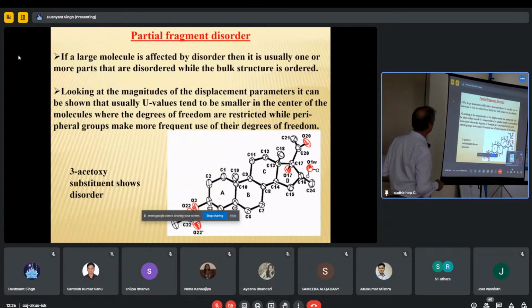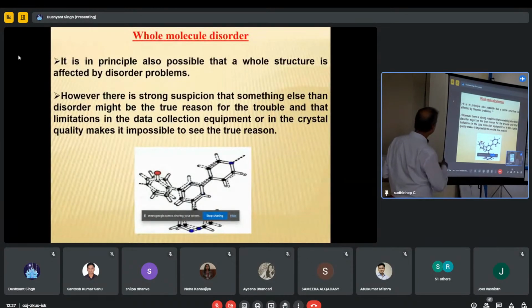Partial fragment disorder. Now, your whole molecule is stabilized with 100% occupancy, but in the acetoxy substituent, one of the oxygens of the acetoxy group is showing disorder. So we have bifurcated it into two parts, O22 and O22 prime. Looking at the magnitude of displacement parameters, it can be shown that U values tend to be smaller in the center of the molecule, however the acetoxy group is showing large thermal parameters. So this is an example of part of the molecule showing disorder.